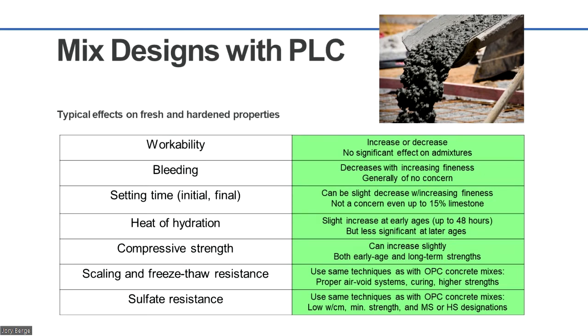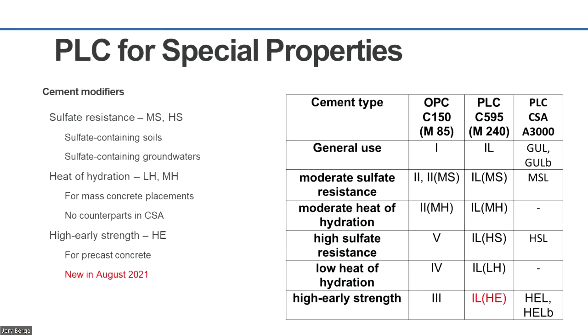And the good news on the durability side is we have a lot of information on long-term performance of these cement types, and we know they're durable. If you're dealing with anything on sulfate resistance and knew about the studies that were performed in Canada about 5 years ago, those were questions based on some frost susceptible aggregates in a belt line in Texas, of all places. And so they were worried about the methylene blue test and those limestones failing it. And they did some sulfate tests on these types of cements and found that everything we were worried about, we were wrong. And it is still proven to have sulfate resistance, which is a very harsh test for those who have performed that. So these materials do work well in concrete. And we have a lot of proof of that.